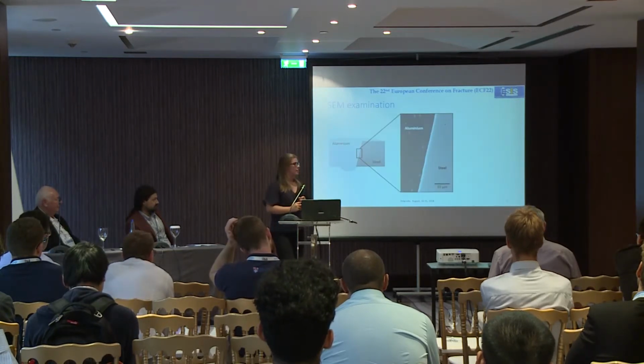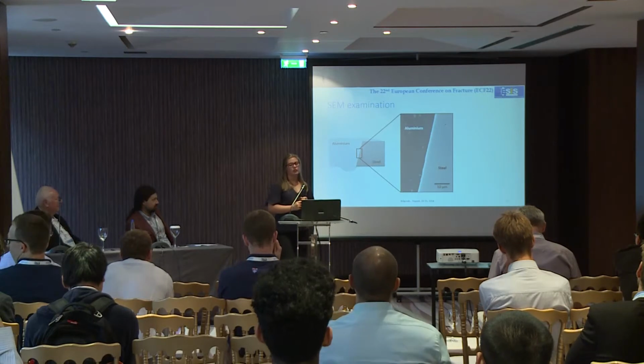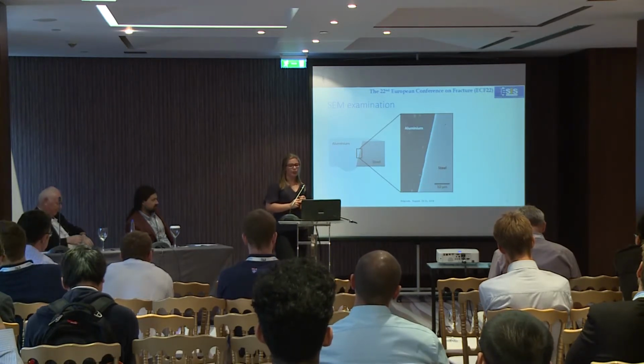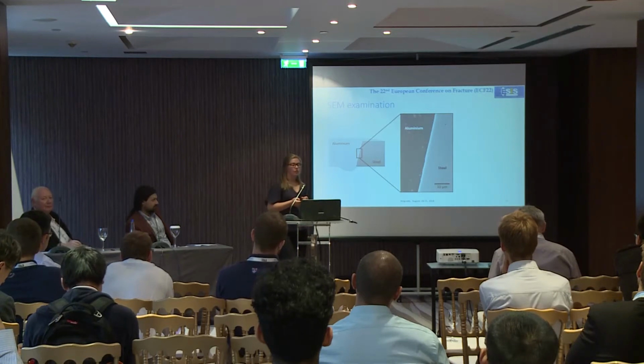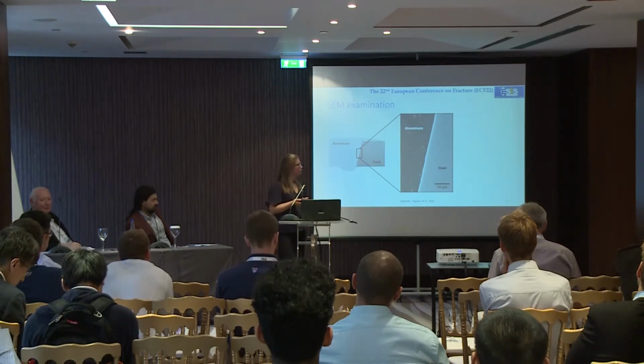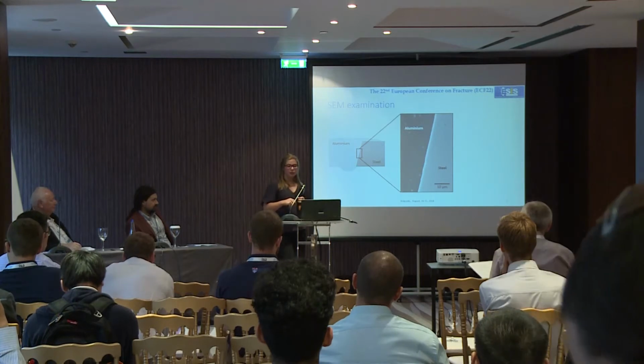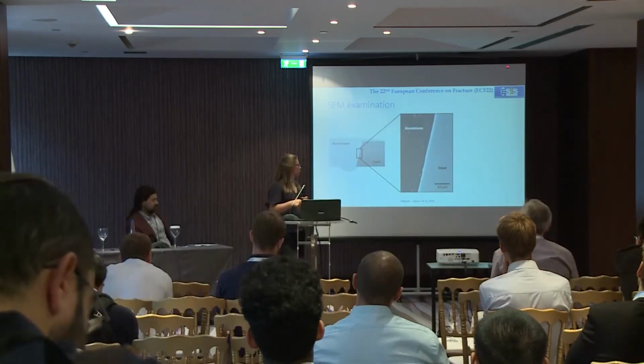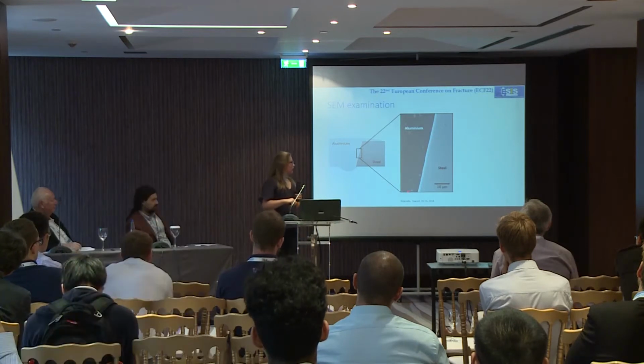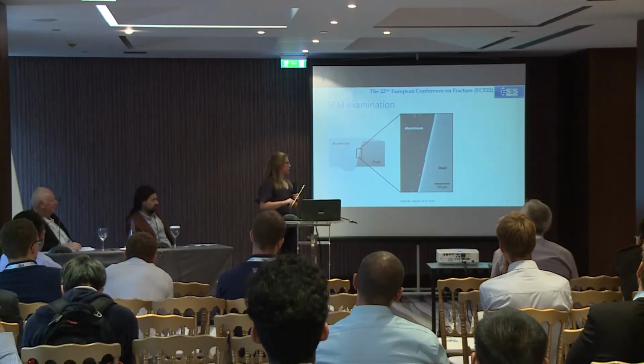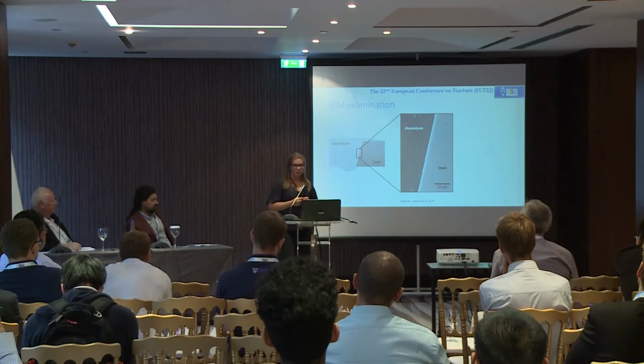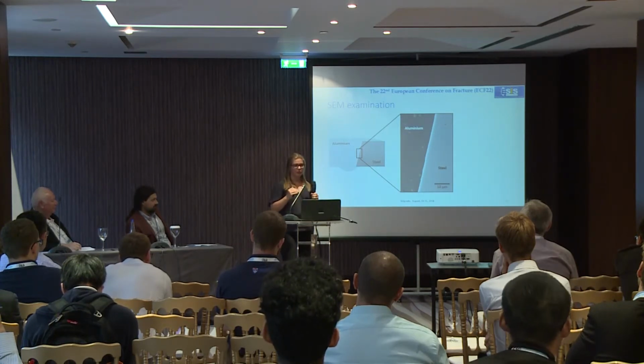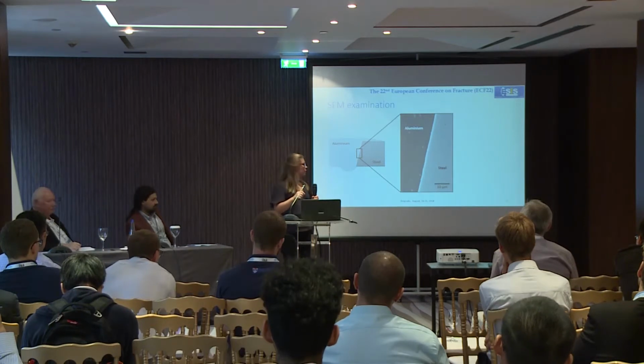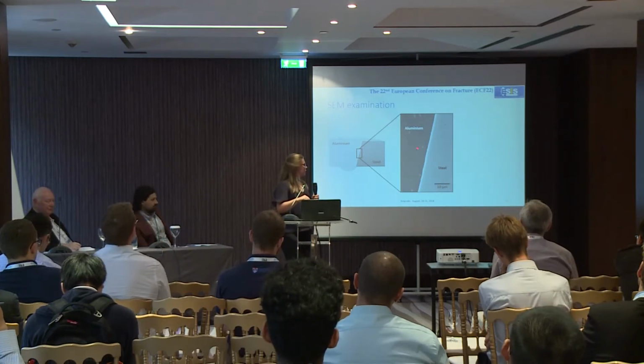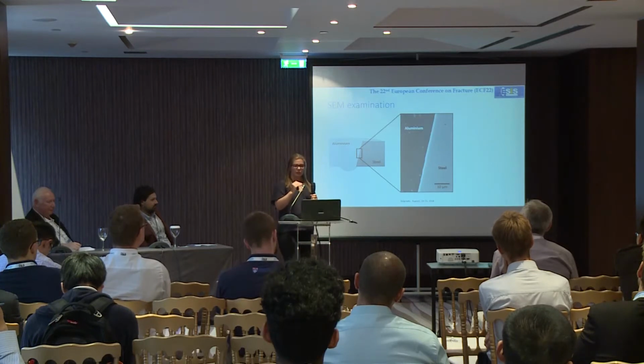Also, we did some SEM examination. This was to see if there was any significant formation of intermetallics along the bond line. But at the highest magnification, which is 8000, we couldn't see anything. And this light area here is mainly believed to be an artificial effect due to the height difference of the aluminum and steel when you polish it. Since the aluminum is softer, the steel will be a bit higher, which is this line.